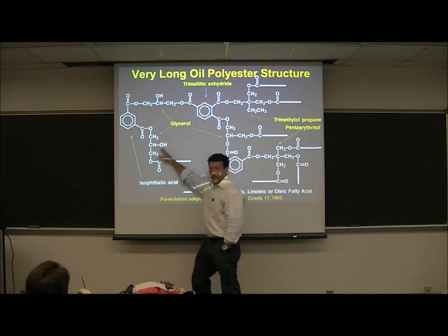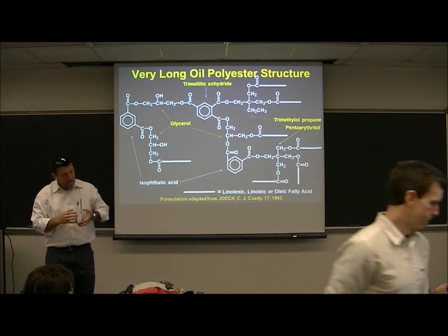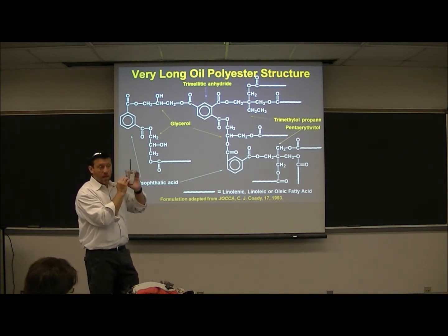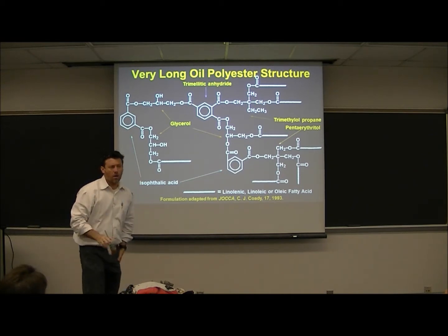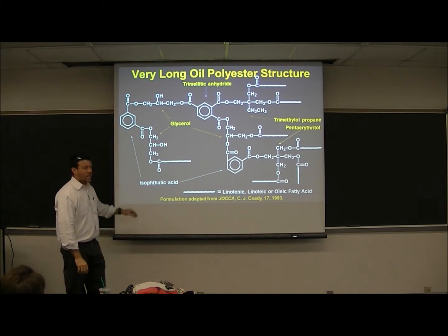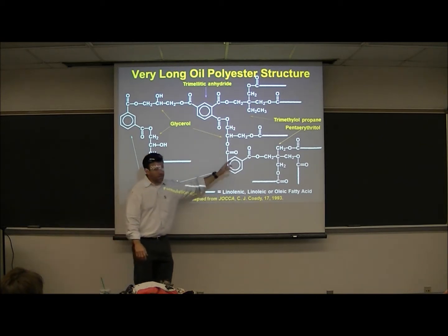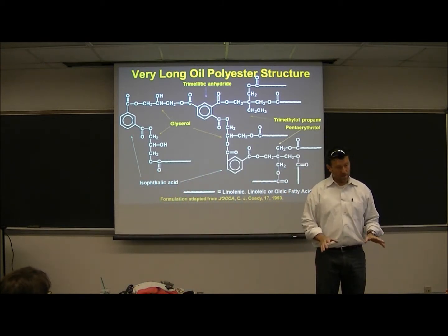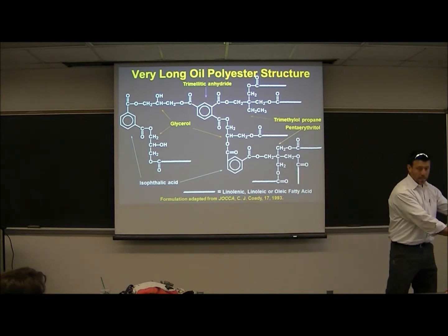we would increase the number of hydroxyl groups so that this was thinnable. We would call it water thinnable. We would still sell it in a can at 100% solids, but we would write on the can that before application, we recommend you thin. And this material is designed to be water thinnable. Now, water wouldn't actually be a solvent then. Water would be a diluent, and it would blend in, but only at certain ratios. And if we put too many hydroxyl groups and too many carboxylic acid groups, even if we thinned it with water, when the film dried, it would be water sensitive. There's a balance of properties. What do we make in a can that you can use that still meets the need in the end?